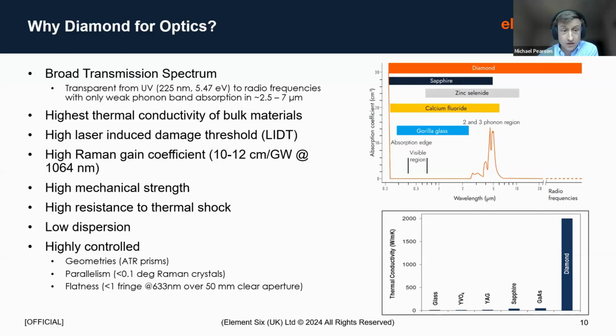Just for a bit of further context, copper, which we would typically use for heat spreader applications and heat sinks, we consider to be a very good thermal conductor. It has a thermal conductivity of about 400 watts per meter Kelvin. So diamond is still blowing copper out of the water in terms of its thermal conductivity. Why does that become important?